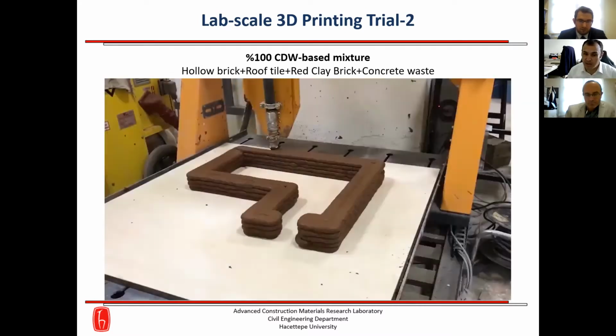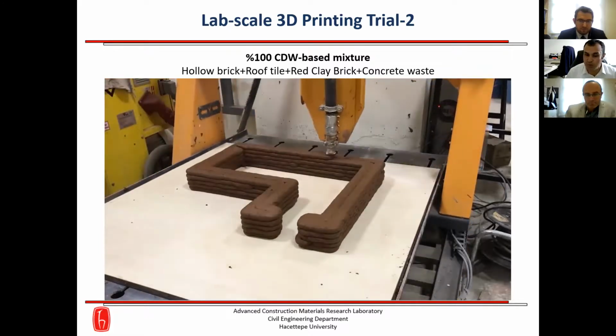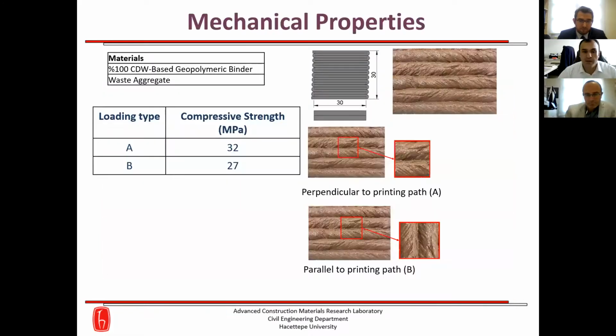And we are still spending our effort to improve the 3D printing system and the development of the methods shown in this video. I also want to mention shortly the mechanical properties, because the methods under the hardened state in terms of 3D additive manufacturing require some special properties. Sufficient mechanical properties in different directions and bond strength between two consecutive layers are necessary in order to ensure printing compatibility of mixtures in the hardened state. And adequate bond strength between the consecutive layers is a vital parameter to maintain structural integrity in additive manufacturing and to resist acting shear stress, especially formed by the earthquake effect, for example.